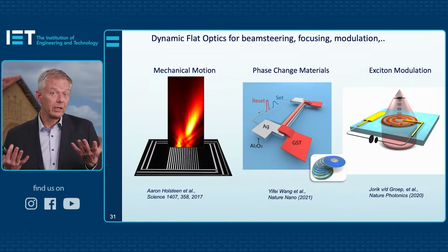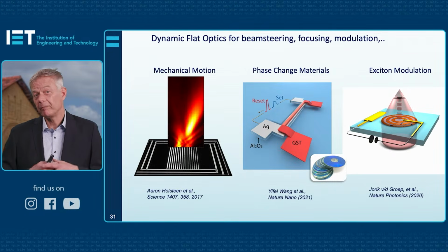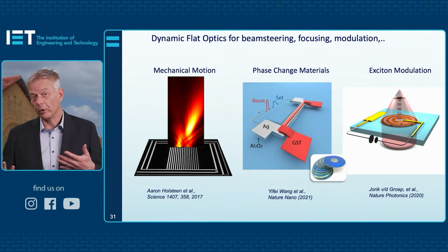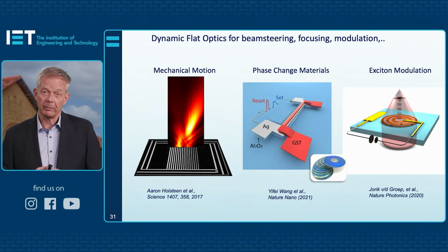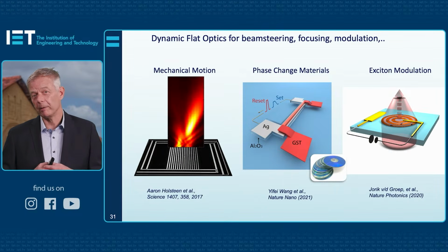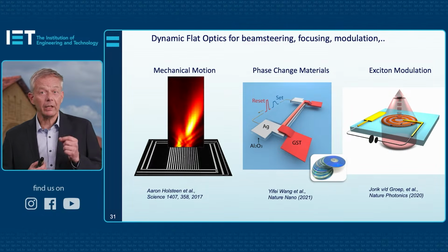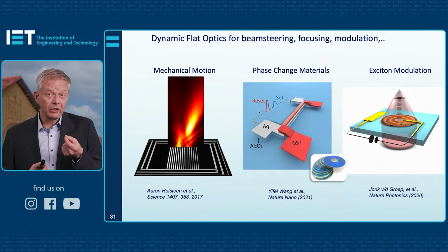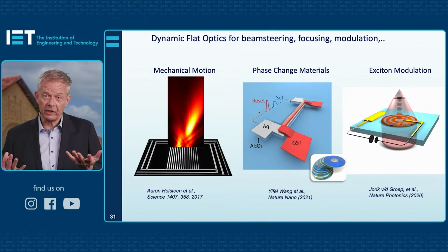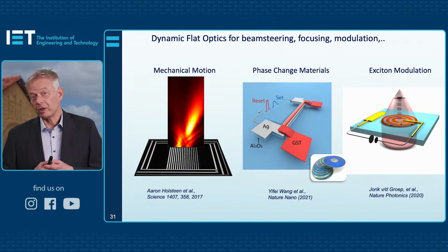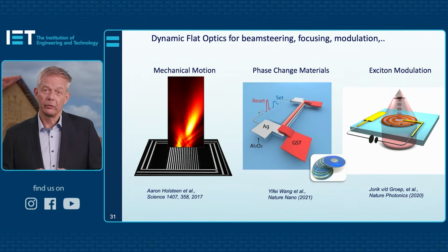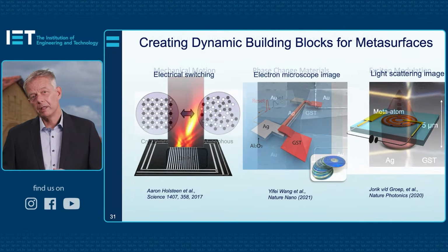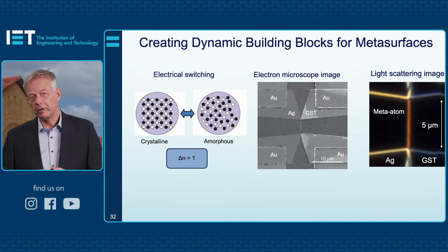That allows us, with little pulses of heat, to change the structural phase back and forth and tune the scattering properties. I'll show you this example in a second. On the right, we also show that excitons, material excitations inside semiconductors, can be used to focus light and to modulate it very effectively. Here's the example of the phase change material.